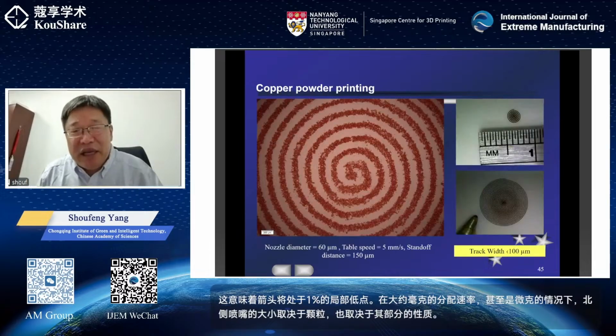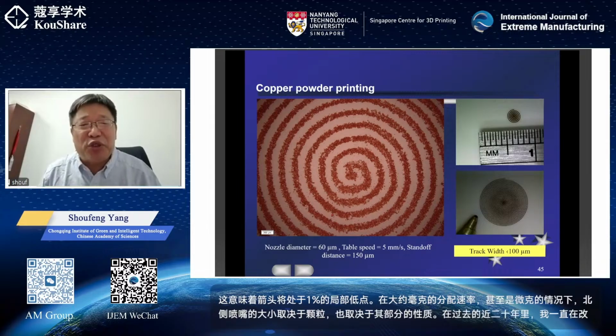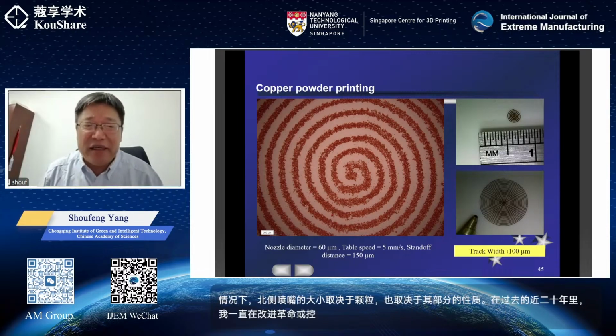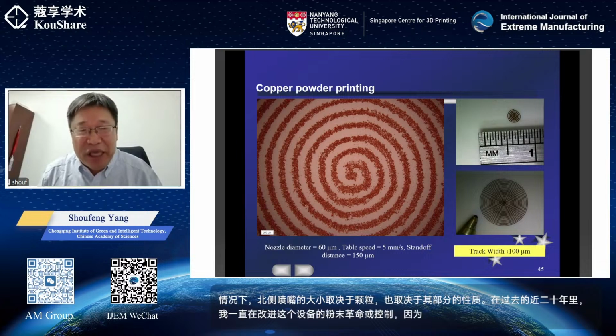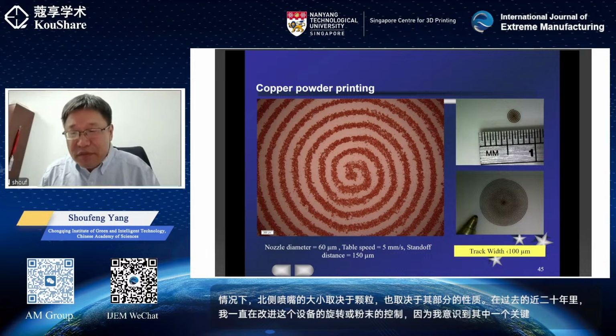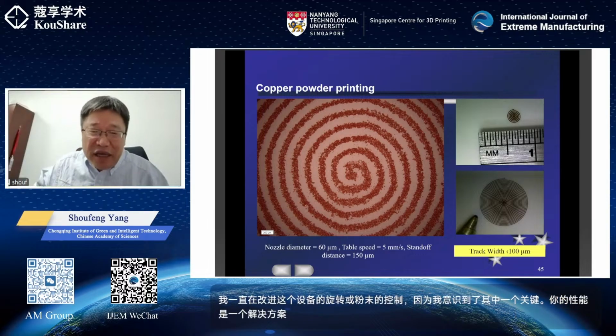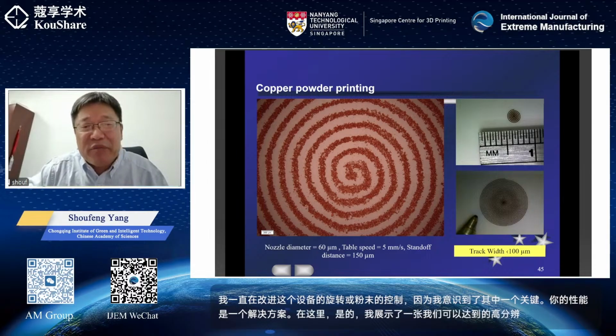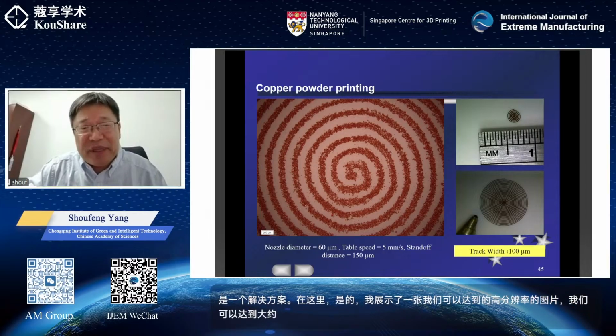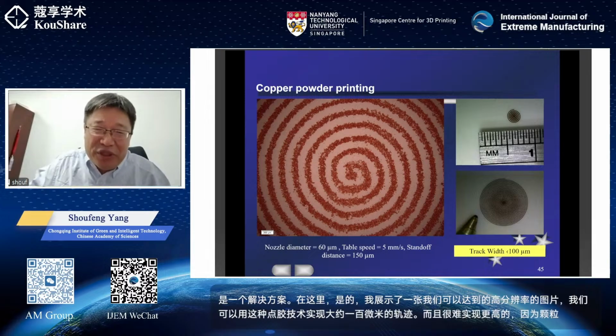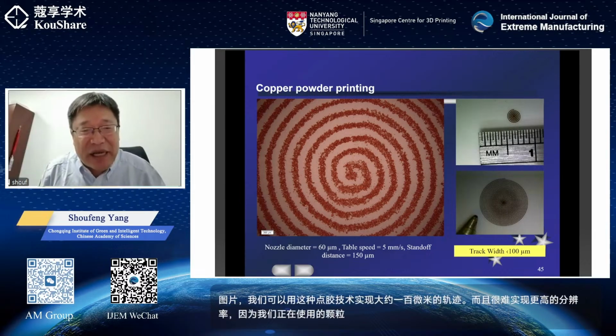And in the last almost 20 years, I keep improving the resolution or the control of the powder from this device, because I realized that one of the key performance measures is the resolution. So here, I show the picture of the high resolution we can achieve. We can achieve about 100 micrometer of track width with this dispensing technology, and it's quite difficult to achieve higher because the particle size is pretty big. We are using 50 micrometer particle size.